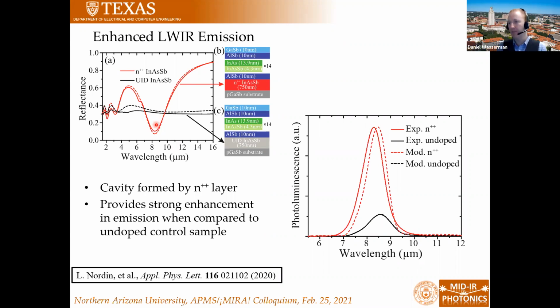So what we're seeing here is a combination of a number of effects, and we go into this a little bit more in the paper, but basically you have a cavity mode, but combined with that, you have a Purcell enhancement. Purcell enhancement is when you have a very large photonic density of states into which you can emit. So you have these plasmonic modes that sit at the interface between your metal and your dielectric, and these are high density of photonic states. So your light wants to emit into that. So you get a very strong decrease in the recombination lifetime, which means that you're emitting more light instead of the light recombining. Now, the reason why we only see a factor of 7 is because all of that light that you're emitting is basically being emitted into plasmonic modes.